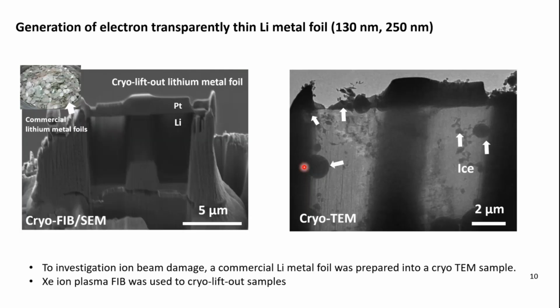So in order to study this, I use commercial lithium metal foils to make TEM samples. Because they are not grown in organic electrolyte, they do not form any SEI on them, so that I can purely study ion beam damage to SEI. And I generated cryo-lift-out lithium with two different thicknesses. One is close to 130 nanometers, and the other one is 250 nanometers. In the meantime, we use xenon ion plasma FIB to study this.